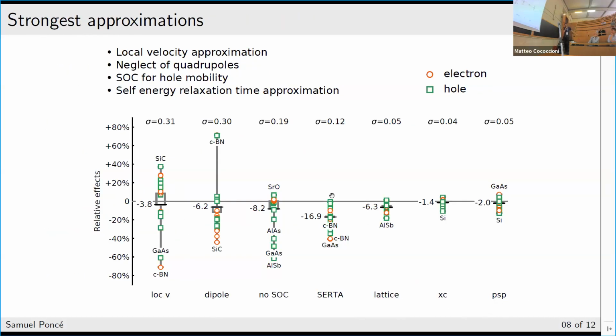There you go. This is not fully answering the question, but somehow. This is for, let's say, 20 cases, 20 materials, electron and hole. Here you see the impact on the mobility of different approximations. In this case, I took the reference of 0 as being the best one that I had, done with PBE and then quadrupole and so on. Then I tested what is the change, relative error but also absolute, if you change something. This is the change that you get if you change the pseudopotential but not the exchange correlation. I tested some libraries, maybe with semicore, without semicore, things like that, but still the same exchange correlation functional.